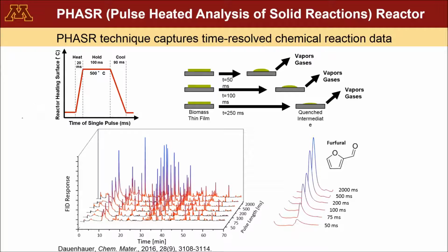With this system, we can take a thin film sample of material, rapidly heat it to the designated temperature like 500 in 20 milliseconds. Then we can hold it at that temperature for a time such as 100 milliseconds and rapidly quench it in less than 100 milliseconds and stop the reaction. So we can stop and start the reaction, analyze the product, and then plot the data as a function of time.